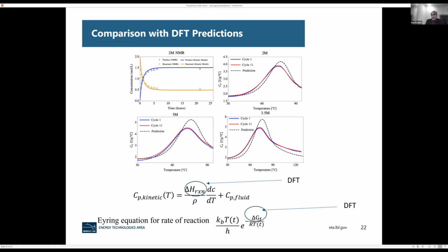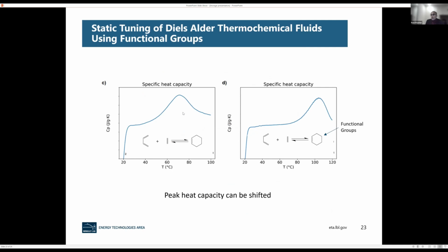We also developed a model based on density functional theory predictions, and from the DFT we can actually predict the transition state enthalpy and entropy and the reaction enthalpy. It matches very, very well with the data. So it gives us a tool now to design molecules at will. And here is one result, for example, based on the DFT predictions. We are designing new molecules where I can exactly tune where the peak heat capacity happens, right? With that, I'm just going to end and we'll be happy to take questions.